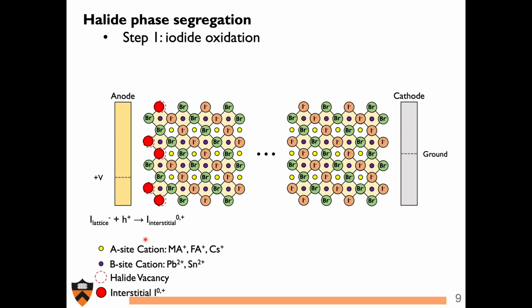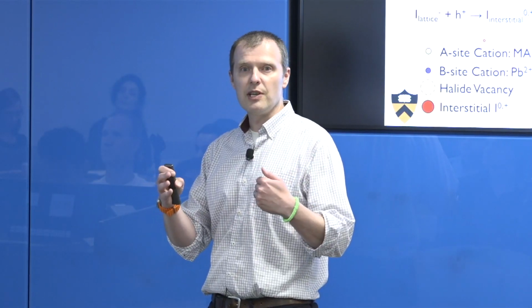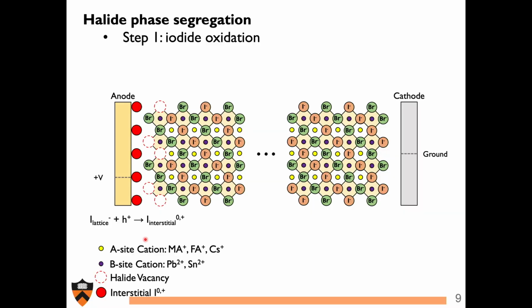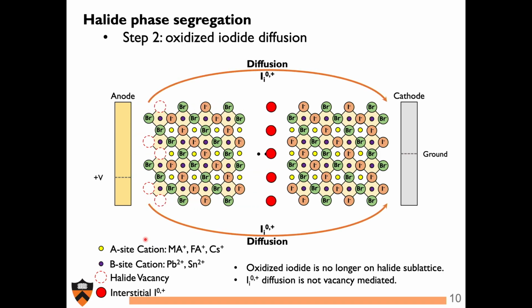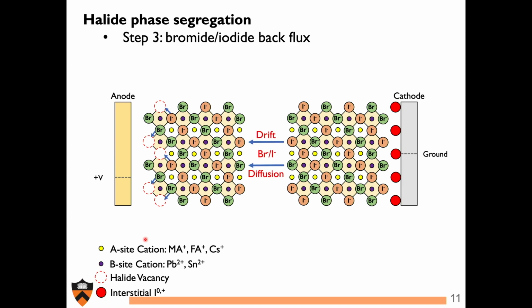They leave the lattice, they make interstitials. And now we have an interstitial diffusive gradient that's going to cause interstitials to move to the right. We also have a field between the positive anode and the negative cathode that could also allow migration of these interstitials toward the right. So whether it's diffusion, whether it's drift, you can think about it as you will. You also now have vacancies. And these vacancies will also be able to diffuse. And those vacancies are effectively allowing bromide to net move toward the left, right? Because the left side is where iodide gets oxidized.